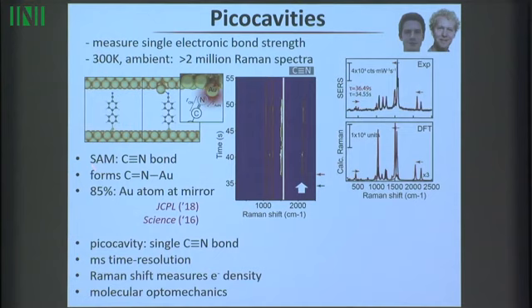Now let me show you an even more interesting problem that we have. So what I can do is I can put some molecules into the gap. I've just shown one of them here, but it's not true. There's a stack of these molecules, and they're all identical. They're very simple molecules. They've got one site on the bottom that anchors them into the gold. This is a sulfur atom here, 2 benzene rings, and then on the top here is a carbon-nitrogen triple bond.